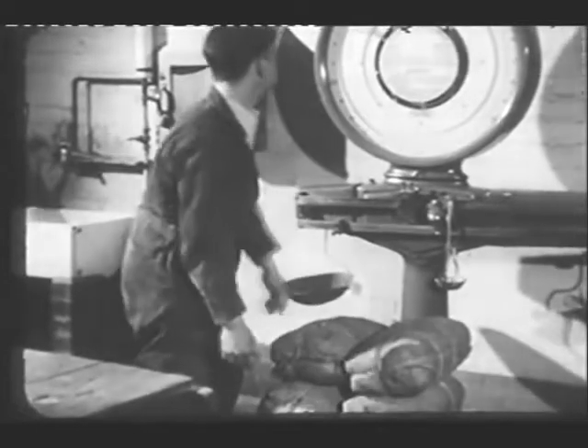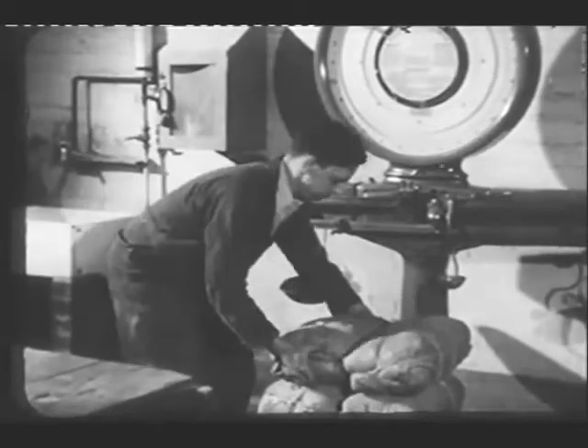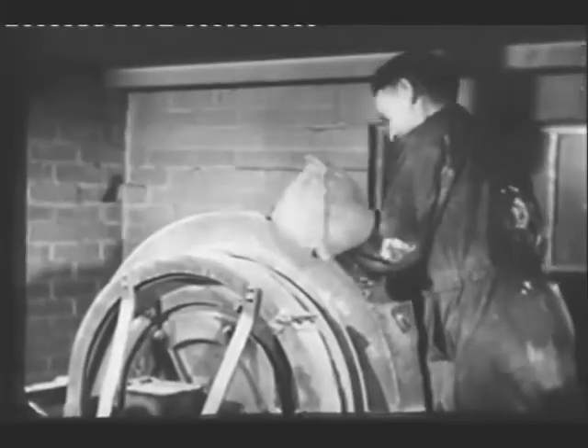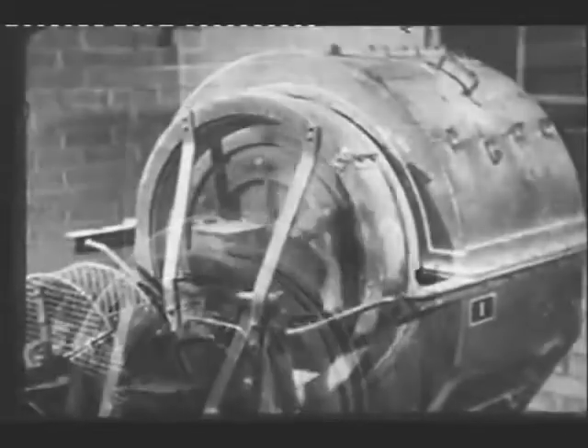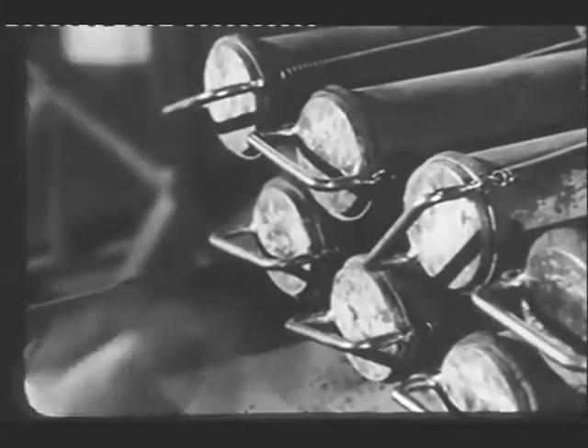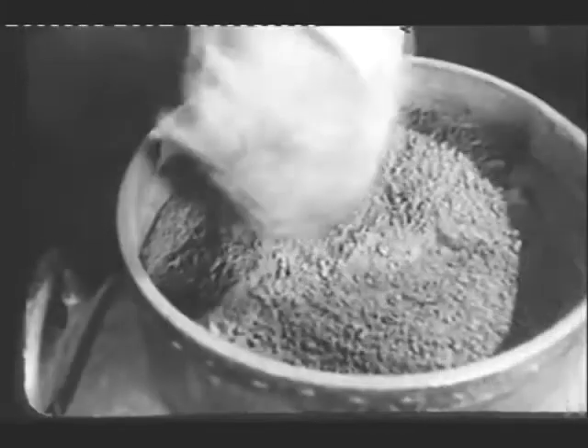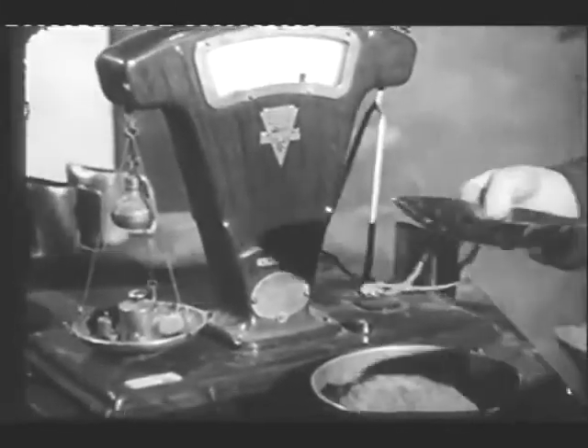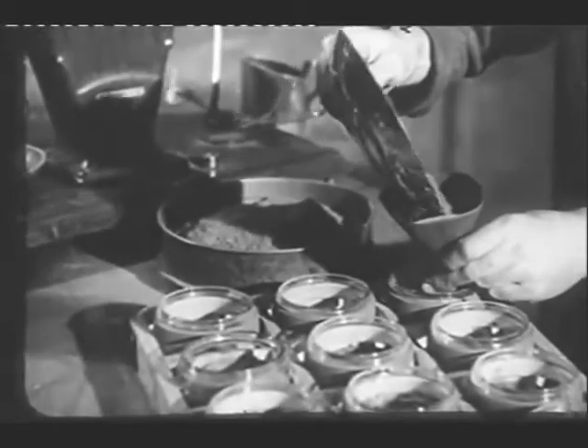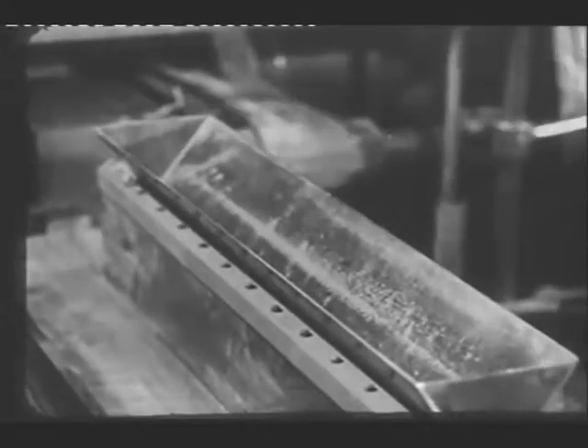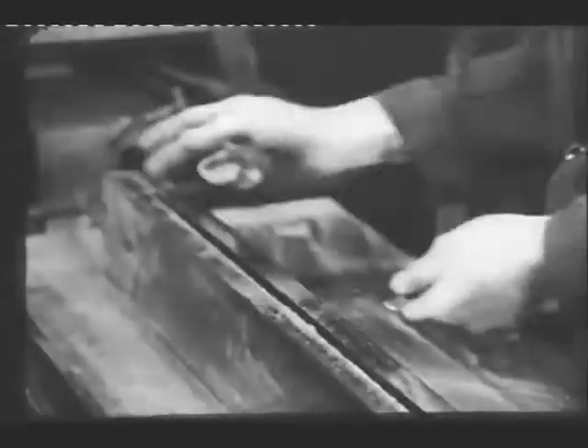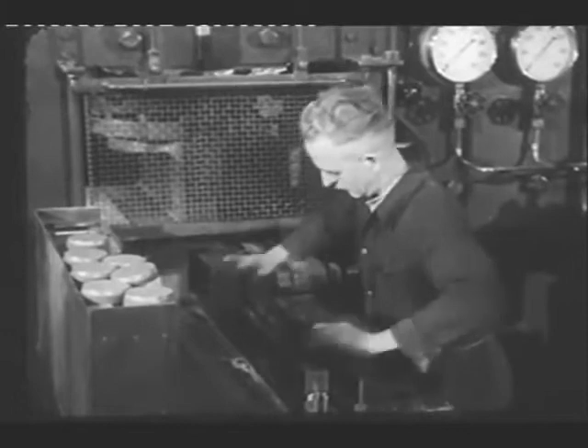The heater is made from tungsten, and tungsten is the metal obtained from scheelite. The scheelite is weighed and tipped into a ball mill. Here it is ground continuously for 7 days to reduce it to a fine powder, which then undergoes various chemical treatments which yield pure tungsten in powder form. The tungsten powder is weighed out into suitable charges. It is placed in a steel mold, carefully leveled, and packed down.